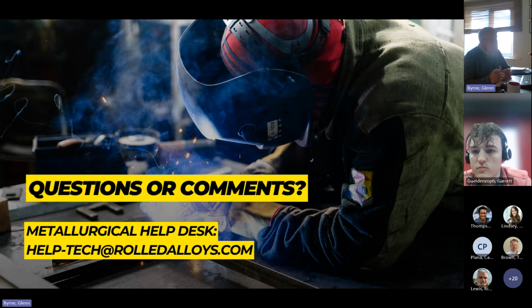But as I say, these days it's mostly if you've got a very large heat sink and you're welding a small component to it with single pass welding, almost, where you see most of the ferrite problems, and you can mitigate that with argon nitrogen shielding gases.